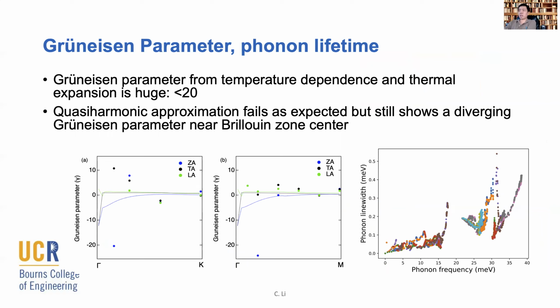we can see that for those ZA modes, here I'm again overplotting the data, the points extrapolated from inelastic X-ray scattering versus what we calculate through the quasi-harmonic approximation with DFT. You can see there's definitely strong disagreement between those two. But one thing in common is we're going to see a divergence of this Grüneisen parameter at regions very close to the zone center, which is the gamma point here.